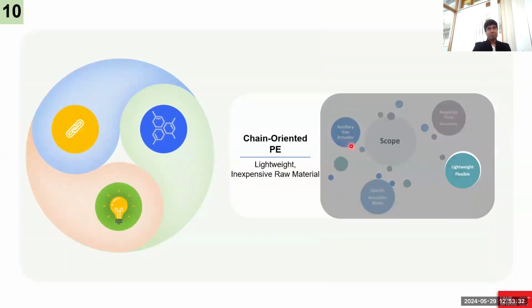The second part of our recipe is to utilize a material as a substrate which we can use to actuate something. And we wanted to create a lightweight and flexible material, and polyethylene comes into our mind, which is easily available. It's a commercially very cheap material, and it's lightweight. And the density of polyethylene is around 0.95, less than 1, making it a great advantage over other materials like SMA and ceramic materials, because the density of those materials is very high as compared to polyethylene.